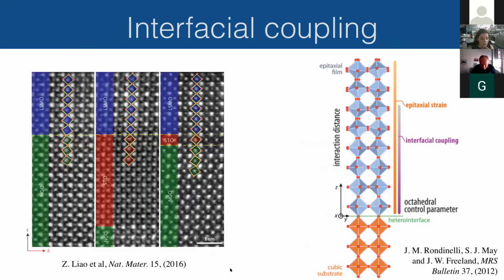So octahedral rotations compose a very active subfield of thin film perovskite oxides all on their own. So this was one beautiful study, but there are so many others. This is yet another scanning transmission electron microscopy image, where these authors found that if your substrate has a different rotation pattern or different rotation magnitude to your film, then at the interface, you can actually impose a bit of this. So here you have LSMO, which is not very distorted in general, but it's quite distorted at the interface